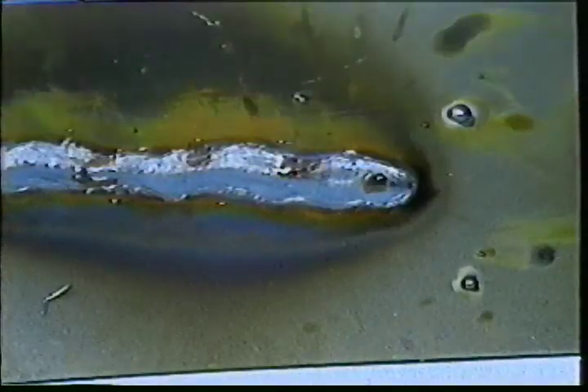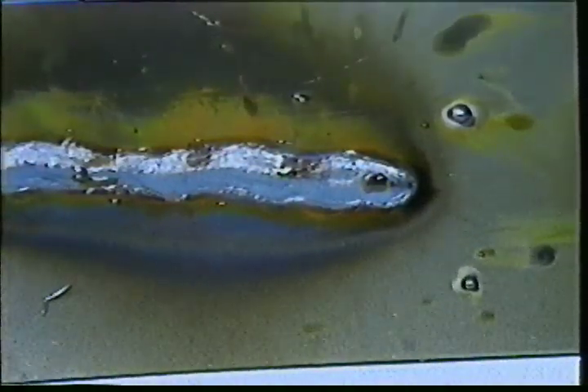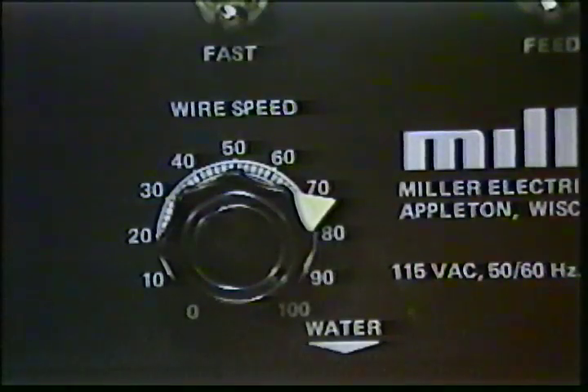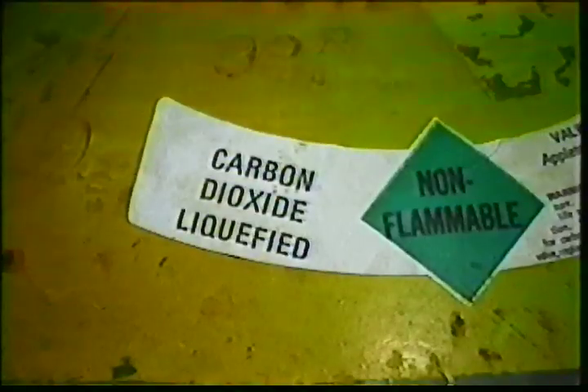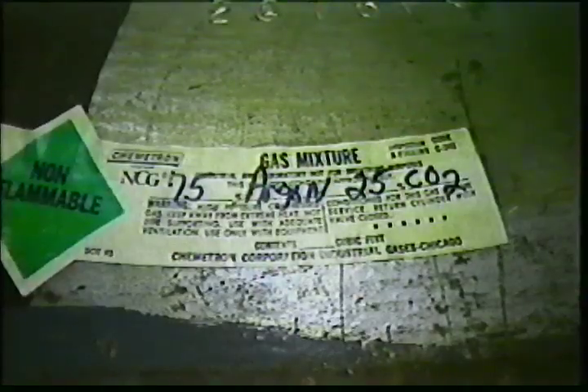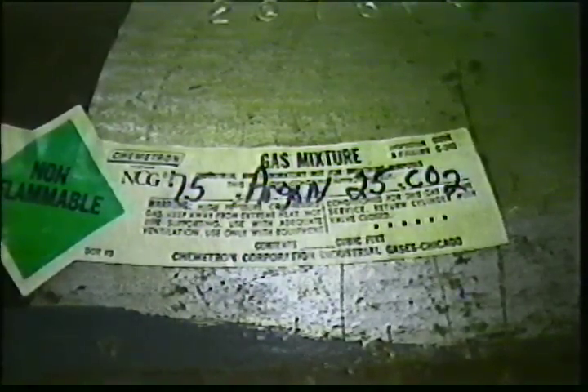While some spatter is normal with short-circuiting metal transfer, a common reason for excessive spatter is high voltage and high wire feed speed. Carbon dioxide is commonly used for short-circuiting metal transfer. However, a mixture of 75% argon and 25% carbon dioxide would decrease the spatter level.